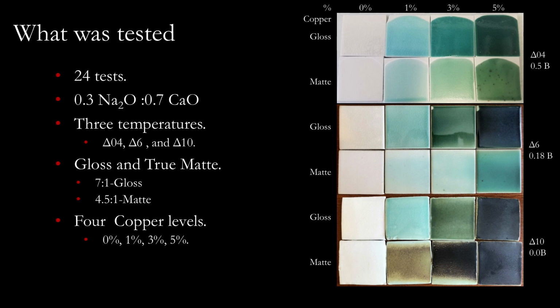The test we had were 24 tiles, all at a constant flux ratio of 0.3 to 0.7, what was listed as our known most durable flux ratio. We did not include copper as a flux because we wanted to see what was going to happen to the durability. There are 3 temperatures we looked at: cone 04, cone 6, and cone 10. These are common ceramic temperatures that people work at. We've got glosses, we've got mattes, and then we've got 4 varying levels of copper: 0%, 1%, 3%, and 5%.